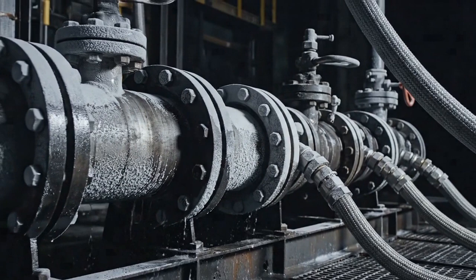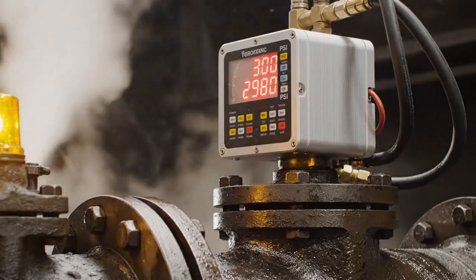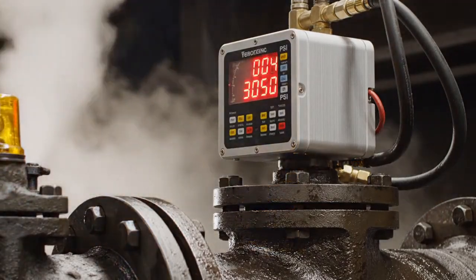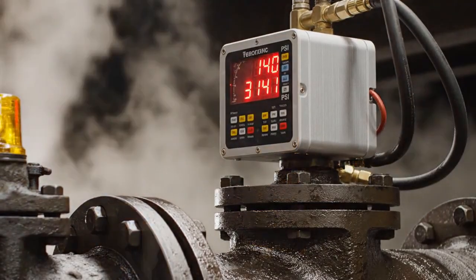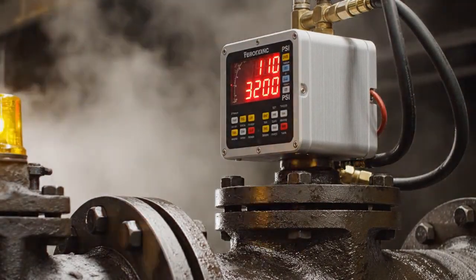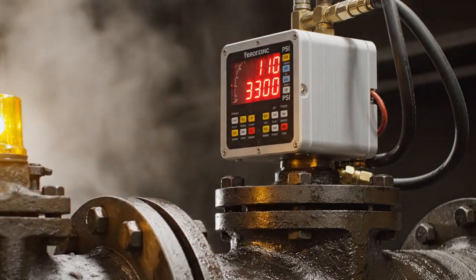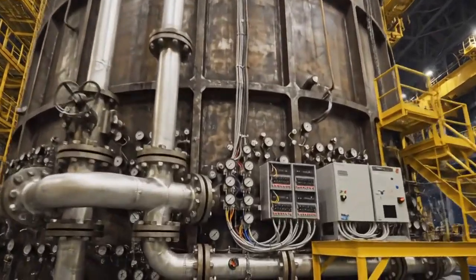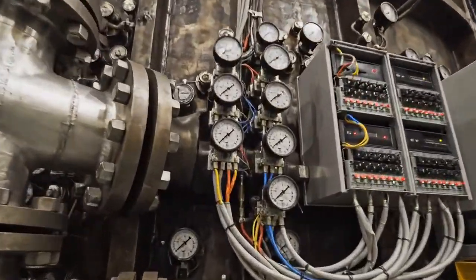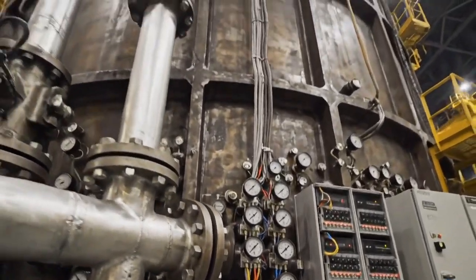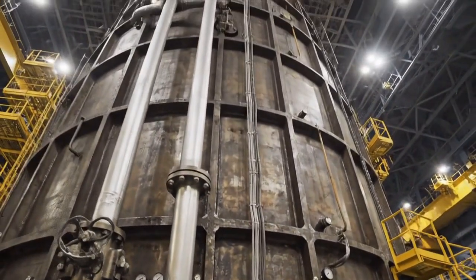Engineers pump chemically pure water into the sealed reactor piping and artificially raise the internal pressure to 150% of its maximum rated capacity, exceeding 3,000 psi. This pressure is held constant for extended durations, while acoustic emission sensors and highly sensitive strain gauges monitor the HY100 steel pressure vessel and its connecting in-canal pipework.